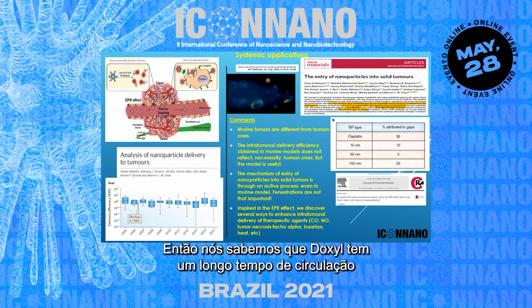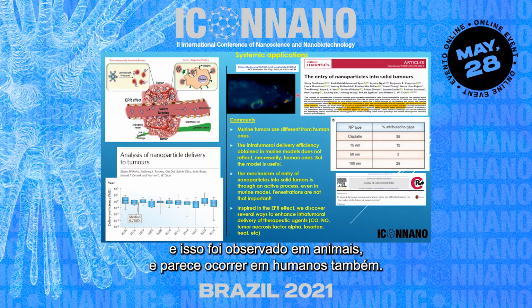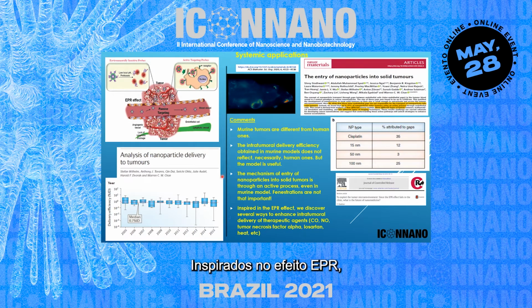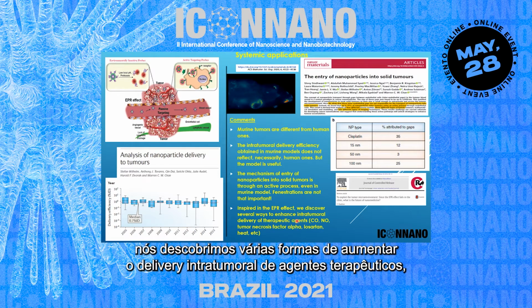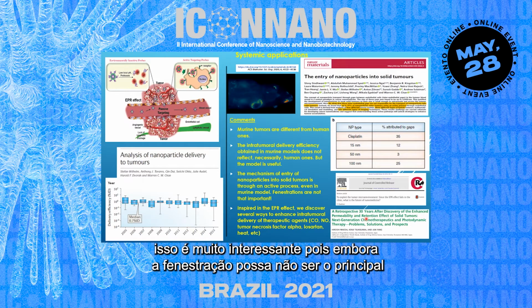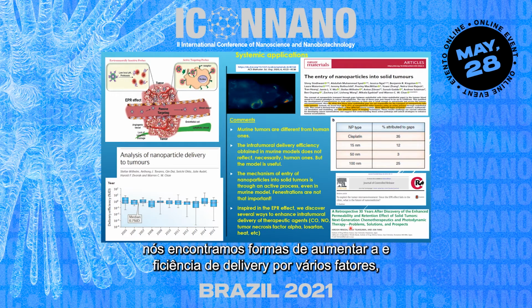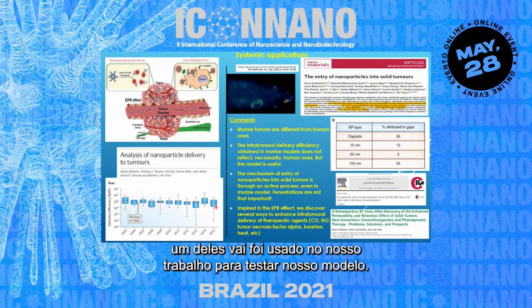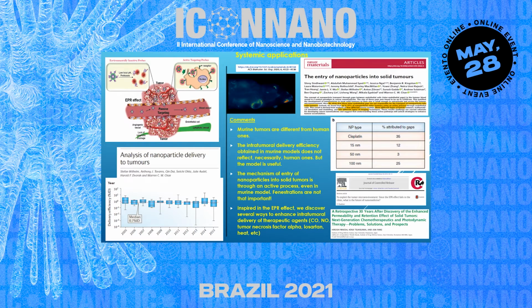So we know that Doxil has a long blood circulation time, and this was observed in animals, as it appears in humans too. And in fact, inspired by the EPR effect, we discovered several ways to enhance intratumor delivery of therapeutic agents. This is very interesting because although fenestration does not seem to play the role, we found ways to increase this delivery efficiency by several factors. One of them we will be using here in our work to test our model.